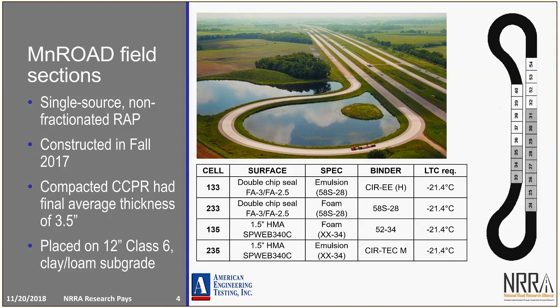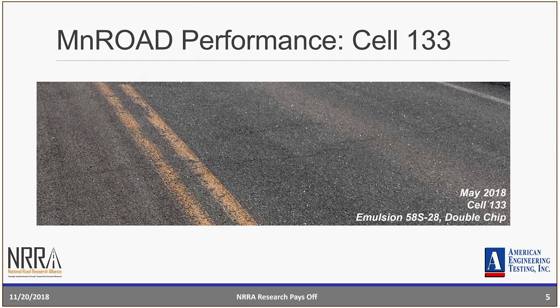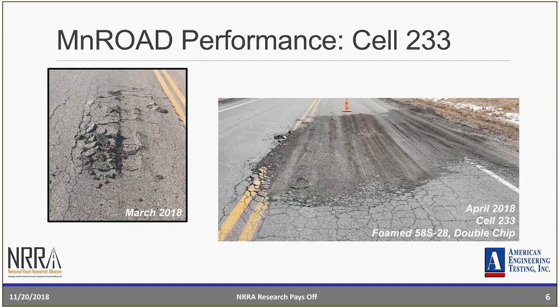So the few sections at MnROAD, I think we've talked about these before. There are 4: 2 have engineered emulsion, and 2 have foamed asphalt. Then 2 are surfaced with a double chip seal, and 2 have 1.5 inches of hot mix. Some early performance is from these cells this spring. The engineered emulsion double chip, and this is just showing you photos that we've gotten from MnROAD, is holding up. However, I think this has been shared earlier. The foam section with the double chip had some issues, but a month later, it's as good as new.